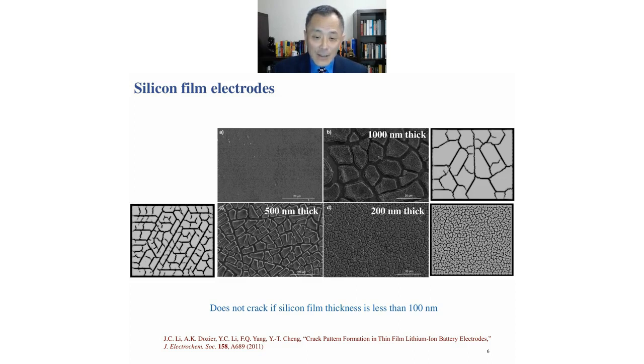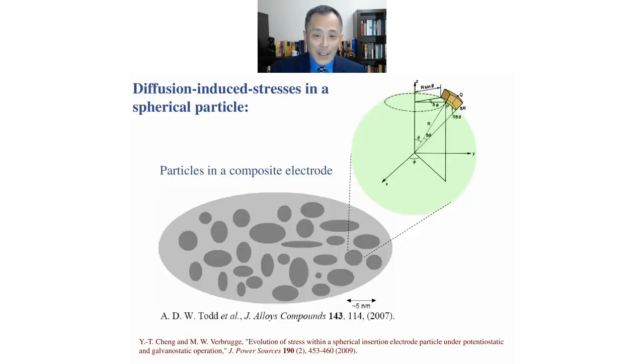And furthermore, the experiments and simulation show that if the film thickness is sufficiently small, less than, let's say, 100 nanometers, cracking can be avoided. But a thin film electrode with less than 100 nanometers in thickness doesn't store much energy. So that is not the practical configuration of a commercial battery.